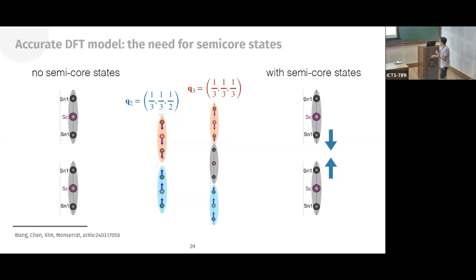And what we think is critical in this system is essentially the C-lattice parameter. And it's really easy to understand why that's the relevant quantity. So this is the structure, and the Q2 wave vector corresponds to these two trimers going against each other. And the Q3 structure corresponds to a group of 3 trimers oscillating with a modulation of wave vector 1/3. So in a sense, this vibration needs more space than this vibration for it to be accommodated in the structure.